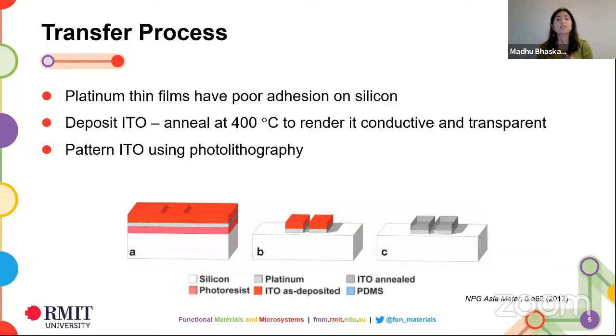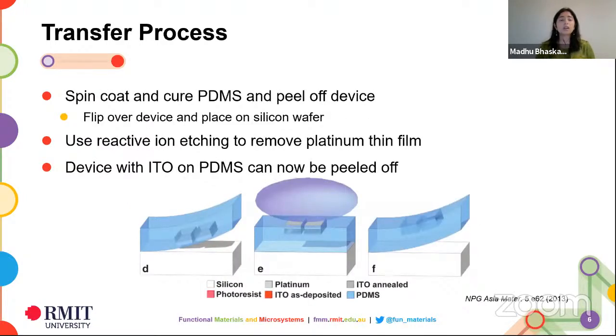Now, because we're still working on silicon, we can deposit any oxide at any high temperature using the standard techniques and then pattern it using the standard techniques, either photolithography or nanofabrication techniques. What you see over there in figure C is the indium tin oxide patterned on top of the platinum sitting on top of silicon. Now we spin coat and cure PDMS, or the silicone rubber, on top of this and we peel it off. Because the platinum is not stuck very well to the silicon, the entire layer just comes off along with the oxide underneath it, along with the PDMS. When you flip it, you have the platinum, the oxide layer, and then the PDMS. We get rid of the platinum layer using reactive ion etching, and now you have your device, which is your indium tin oxide sitting within the PDMS.